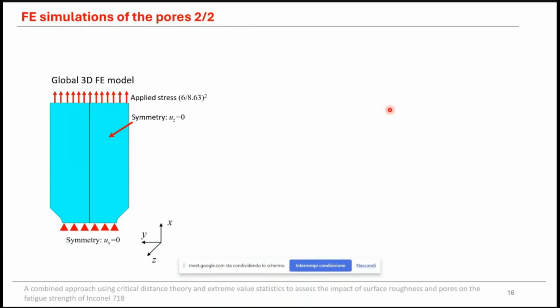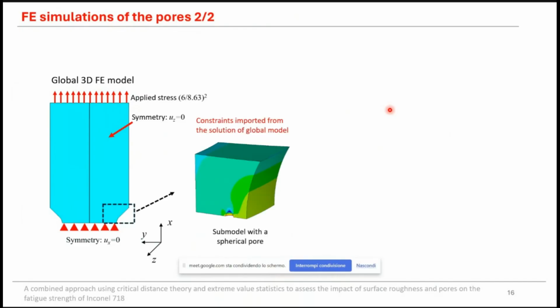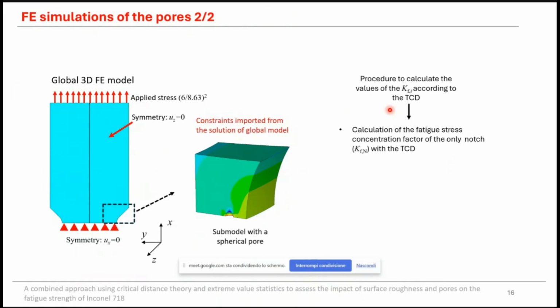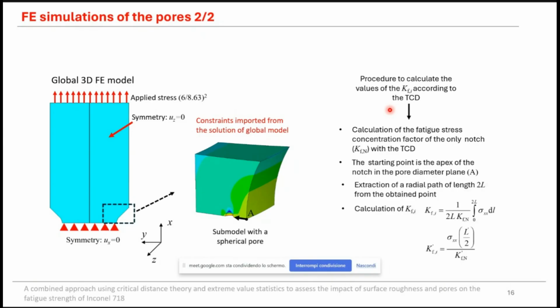The same reasoning was implemented also for the V-notch specimen, but in this case, after finite element simulations, we had two stress concentration factors, one given by the pore and one given by the notch. And given that we wanted to obtain the fatigue stress concentration factor given by the pore only, we firstly performed 2D finite element simulations of the notch only, and we calculated the fatigue stress concentration factor provided by the notch with the theory of critical distances. Then we came back to the 3D finite element simulation. We extracted the radial path starting from point A, and then we calculated the fatigue stress concentration factor of the pore only by normalizing by the fatigue stress concentration factor of the notch only.